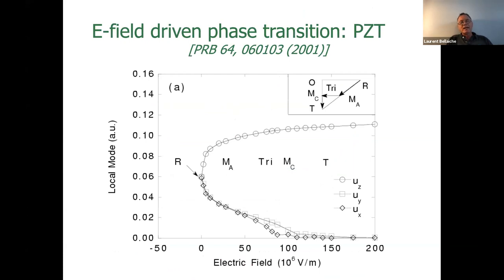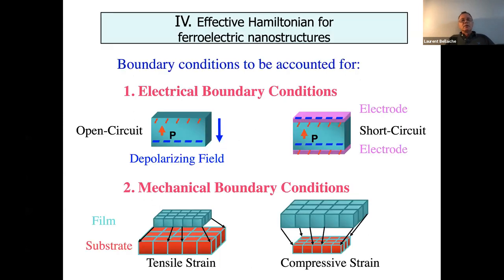For instance, we wanted to have an idea: if you start with PZT in, let's say, a rhombohedral state, polarization along 1,1,1. You apply an electric field, and you increase the magnitude, but along 0,0,1. At the end, it's for sure you're going to have a tetragonal phase because of the minus P dot E term. Polarization will be along 0,0,1, but in between, you don't know how you go from R to T phase. And the system got crazy. It went through a lot of different phases. Two monoclinic phases that are known as MA and MC, but also a triclinic phase. And because of that, you can have very large responses because polarization is basically rotating there. And now we understand that if polarization is rotating, piezoelectricity is pretty big.